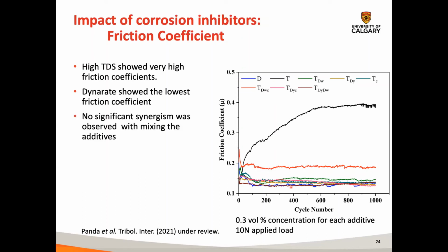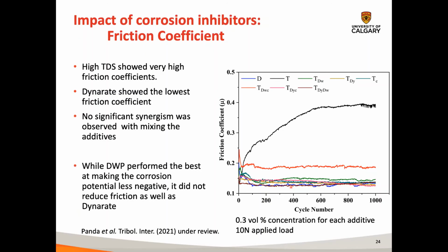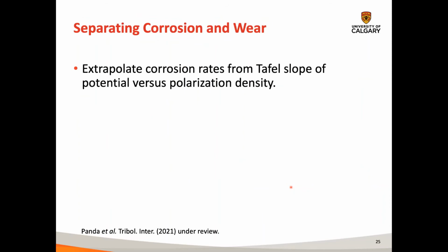And we didn't really see that if you mix 2 different kinds of additives together, there wasn't really a change in the friction coefficient. So while DWP performed the best for reducing corrosion in terms of the potential, Dynarate performed better for reducing the friction coefficient.